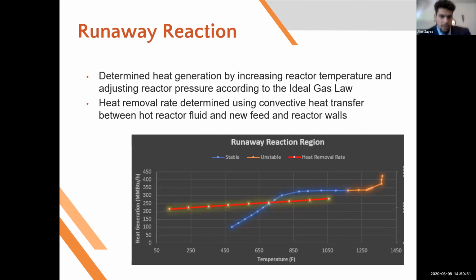The way we figured this out was, as you can see on this graph, the first curve, the blue curve, shows our reactor heat generation that comes from our reactions, which was calculated through ChemCAD. The orange area is where it becomes unstable, around that 1200 degrees Fahrenheit region. The red curve is our heat removal rate, which was determined using our convective heat transfer equation between the hot reactor fluid and the surroundings, which includes the new feed that enters the reactor, as well as the reactor walls. Now that I'm thinking about it, we possibly could have also considered the heat removed by the catalyst, but I didn't have enough information to determine that.